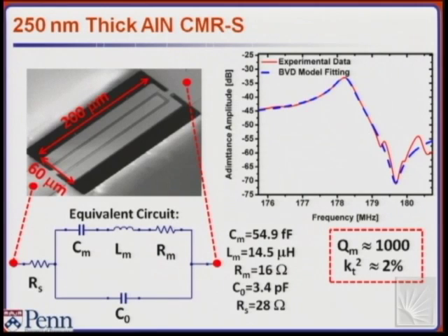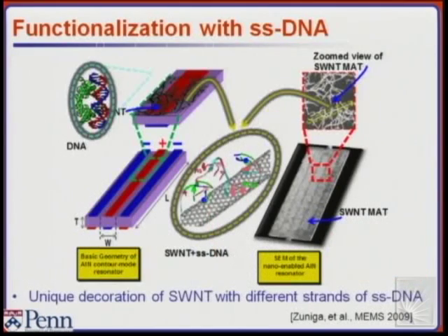So this is a 250 nanometer thick film, which has basically maintained similar performance to the 1 or 2 micron thick films, but is now 4 to 10 times thinner. So it will have 10 times better limit of detection than a higher frequency, higher thickness device. And this RS of 28 ohms, as you probably understood already, is due to the fact that we have long lines and metallic vias that probably did not work the best during that fabrication run.